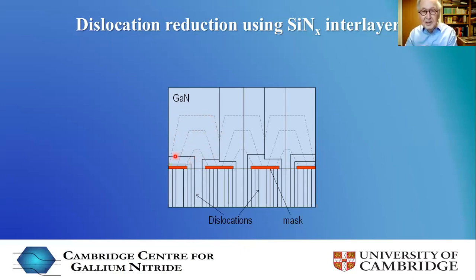If you're lucky, a dislocation which comes up and bends sideways interacts with a dislocation which comes up from a neighboring hole and bends sideways in the opposite direction. These two dislocations come together and they either annihilate or form one dislocation. This is another dislocation reduction mechanism. You may think that's an extremely unlikely process, but actually it's not, and it really gives a significant reduction in dislocation density.